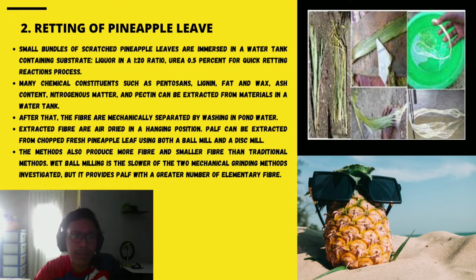Small bundles of scratched pineapple leaf are immersed in a water tank containing substrate liquor in a 1:20 ratio, with urea at 0.5% for a quick retting reaction process. Many chemical constituents such as pentosans, lignin, fat and wax, ash content, nitrogenous matter and pectin can be extracted from the material in the water tank. After that, the fibers are mechanically separated by washing in pond water. Extracted fibers are air dried in a hanging position, and PALF can be extracted from chopped fresh pineapple leaf using both a ball mill and a disc mill. And the method also produces more fiber and smaller fiber than traditional methods. But ball milling is the slower of the two mechanical defibrating methods investigated, but it provides PALF with a greater number of elementary fibers.